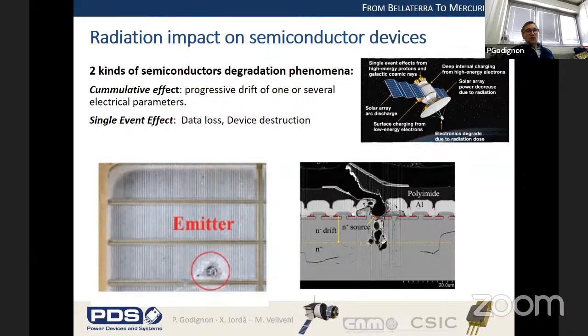So, for instance, in the bottom picture, on the left side, you can see the top view of a device, and in this red circle you can see that there is something wrong in this device after a single event effect. If you do a cross section of this device, so you make a hole inside and look transversally, this is the right picture: you can see a metallic aluminum layer where you have a big hole, and also in the bottom layer, which is the silicon semiconductor layer, you have a very big void. So obviously this device is not working properly anymore, and it was probably caused by only one particle. We have to deal with this, especially for applications in the energy field or in space.